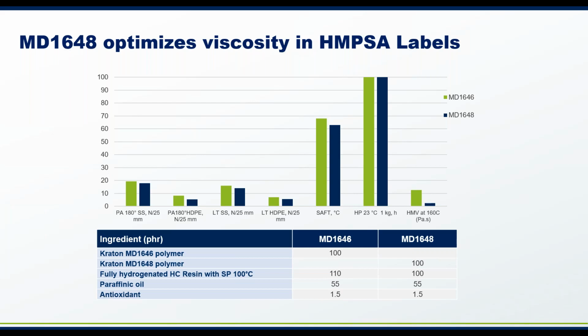In addition to improving adhesion strength in textile, MD1648 can also optimize viscosity in hot melt pressure sensitive adhesives for labels. The chart here compares the performance of two formulations, one with MD1646, which is the green bar, and the other with MD1648, which is the dark blue bar. And using different testing methods, such as quick adhesion, loop tack, shear adhesion failure temperature, holding power, you can see that the MD1648 achieves very similar adhesion performance compared to MD1646, but the MD1648 offers a much lower hot melt viscosity.